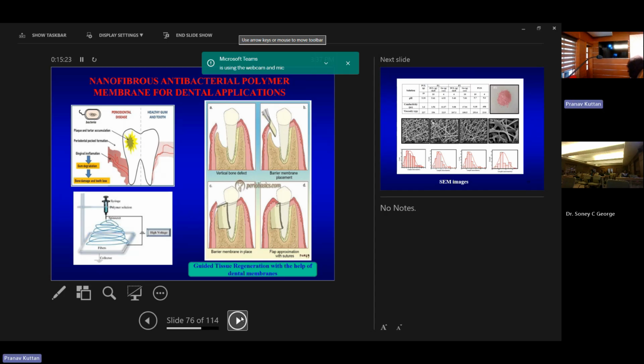Again, for that purpose, we have chosen a polycaprolactone and gelatin mixture. The reason for choosing this kind of mixture of synthetic and biomaterial like gelatin is that gelatin has a highly biocompatible nature, but it doesn't have strength, whereas polycaprolactone has enough mechanical strength, but it is of synthetic origin. So if you mix these two things, you can get mechanical strength, as well as the degradation also will happen.